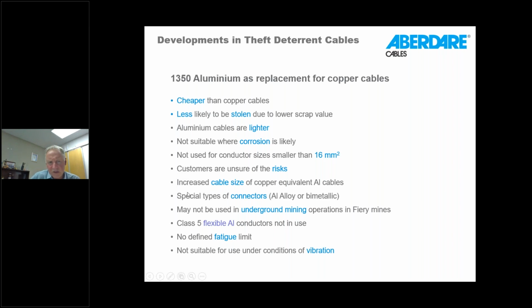The increased cable size of copper-equivalent aluminium cables can cause issues. Sometimes you have to increase the size of a replacement cable for copper up to 2 sizes larger, and that creates issues with bending radiuses when you want to install in switchgear and so on. So it can become an issue where you have tight spaces in which to install these cables.